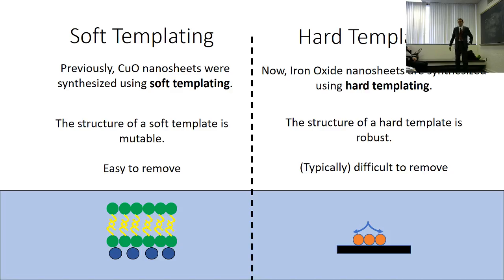I want to draw a distinction between what I'm doing here and what I did in the last work. In the last work, to make copper oxide nanosheets, I used a soft templating method. There are surfactants, which self-assemble in the solution. A lot of people do this sort of thing. And the reason they do it is because you can make a lot of different structures using it. A soft template is very changeable. You can change it based on the solution environment. Change the pH, change the temperature, all these things change the structure of the soft template.